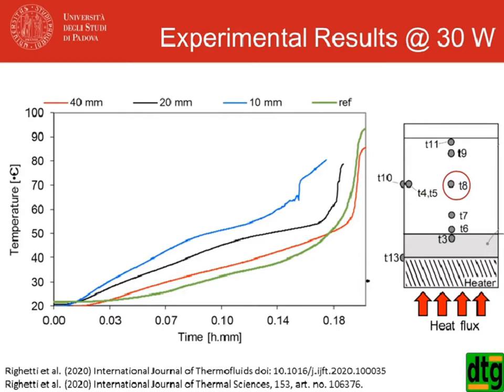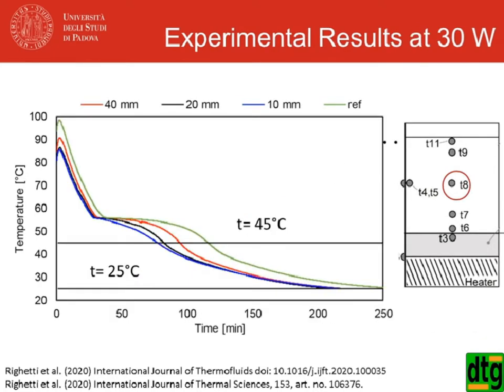Here you compare the different samples. Finally we reach an optimum pore size. So the 10 millimeter pore size revealed to be the best one. And then the performance got worse, okay, passing from 20 and then to 40 millimeters, as compared to the reference one, which is in green here, and it is the reference box. This is the temperature T8 at the center of the box, and you can see here the heat is imposed from the bottom. This behavior remained the same also in solidification, as you can see here, and the solidification was run by natural convection, and again we obtained the best performance with the 10 millimeter sample.